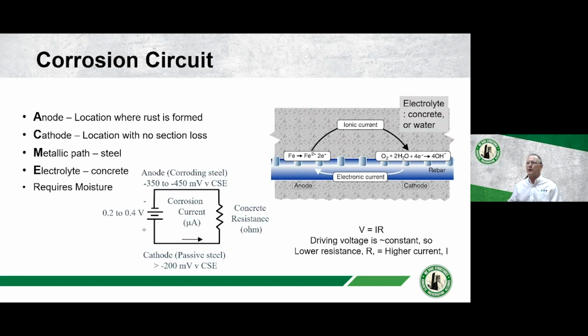All right. So here is the corrosion circuit. We went over the anode, cathode, metallic path, and electrolyte. Well, the chemistry that occurs at the anode is the oxidation of iron. So iron, your reinforcing steel, in a solid will be dissolved and turned into an ion. A ferrous ion is Fe2, ferric is Fe3. And then you release electrons. They run through the reinforcing steel to the cathode, where you reduce oxygen.